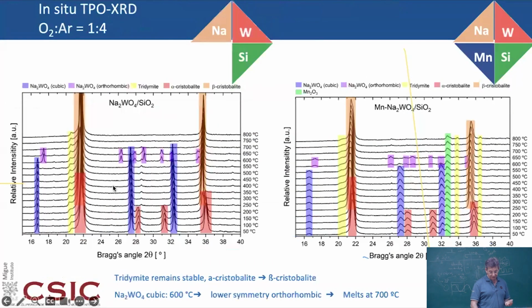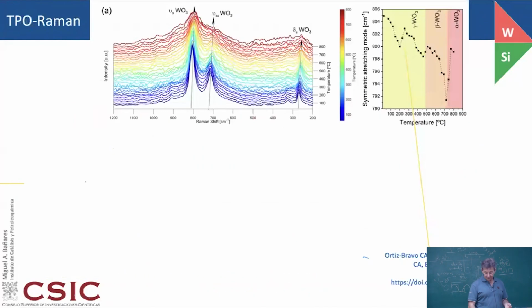These, you already saw yesterday. An interesting point is that above a given temperature, you no longer get diffraction patterns of the sodium tungstate because it's molten. Then it is a liquid phase, and it is the one working on this reaction. You put manganese, and at the moment at which things melt, it changes, but anyhow, it's like 50 degrees higher or above. When you are up there, everything gets molten.